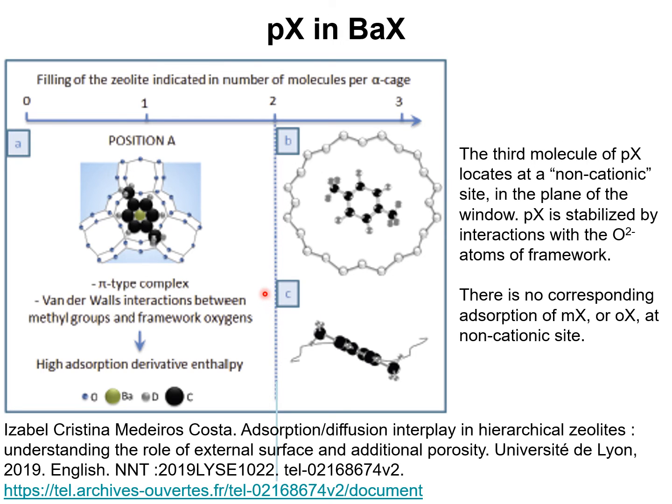So, summarizing, the difference in the adsorption of meta-isomer and ortho-isomer with the para-isomer is that with the para-isomer, the loading of 3 molecules per α-cage is more easily achieved than with the ortho and the meta-isomer, for which the location of the third molecule per α-cage is an energy demanding task.